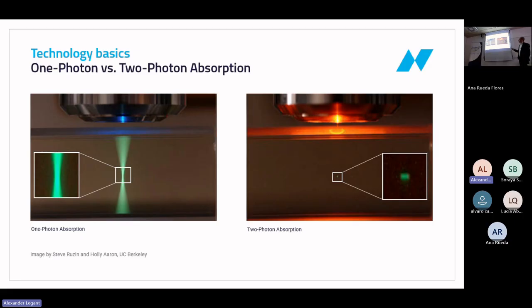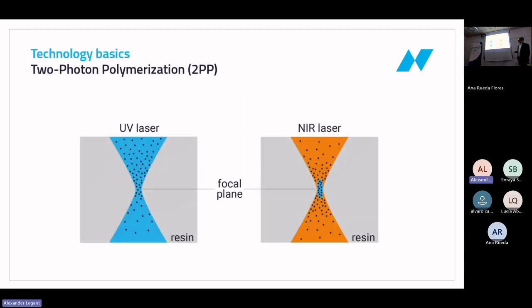So what you need is two photons at the same time at the same place. And the probability for that is only high enough at the laser focus. And if you now exchange the fluorescent dye for the monomer, then again the same happens on the left side: with a blue or UV laser, if the laser power or the dose is high enough, then polymerization takes place in the whole volume.